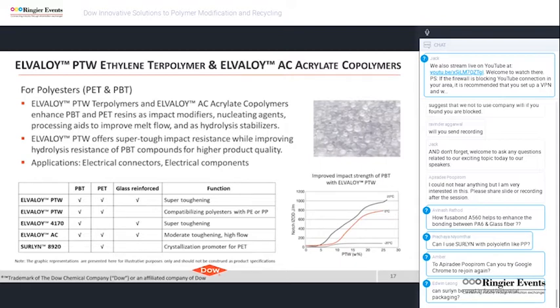Elvaloy AC and Elvaloy PTW are the toughness and hydrolysis stabilizers for polyesters. With Elvaloy PTW, we can reach super toughness, but viscosity is increased. Elvaloy AC leads to acceptable toughness at low addition levels and provides the added benefit of enhanced flow. A combination of both leads to high toughness at moderate flow penalty compared to the unmodified compounds.